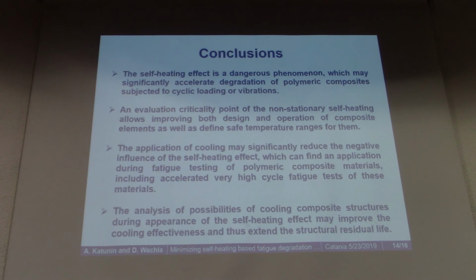Another direction is very high cycle fatigue tests of these materials. Generally we are working with accelerated very high cycle fatigue tests in cooperation with our partners from Freiburg, Germany. There is a problem because we are loading at ultrasonic frequencies, and during this process the heat-up is really significant. This work in particular is a step toward solving the problem by cooling down the specimen during this process.